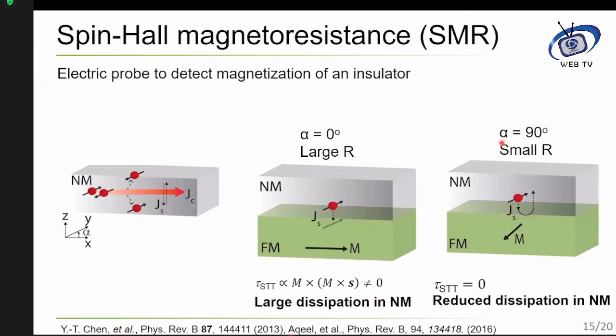What happens is you are sending a current through a normal metal, and spin up will go here and spin down will go here, and you will create some accumulation. This accumulation can talk to your magnet. Although the magnet is a magnetic insulator and no current can go inside, the spin can talk to the magnetization of the magnet. When the spin is perpendicular to the magnet, it can exert a torque, which is called spin transfer torque, flowing into the normal metal. The resistance will be large. When it's parallel, it will be reflected back, and it will be small resistance. So this is the basic principle of the spin Hall magnetoresistance.